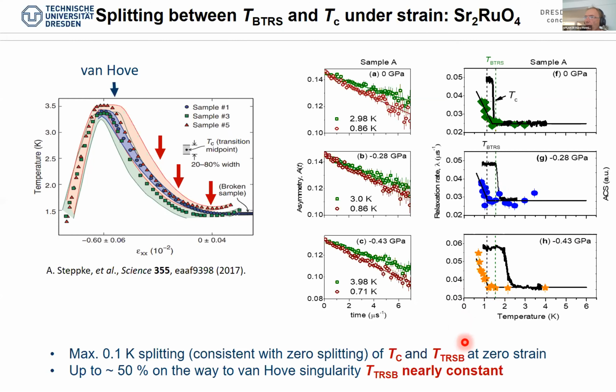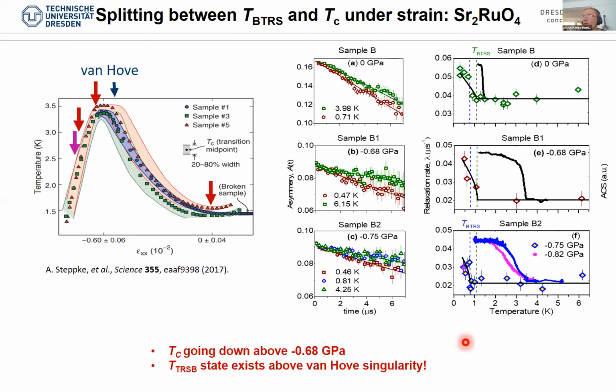If one looks a bit more closely, there is some change at low strain, but I don't want to go into details here. So if we go to higher strain, and now if you look here, I have to go very slowly on the left side. So we cross above the Van Hove singularity actually. So here on the top, again, you see the zero strain point, but now we have this very high strain point here. We still have high TC here, of course, now above 3.4 Kelvin. And then still we have time reversal symmetry breaking.